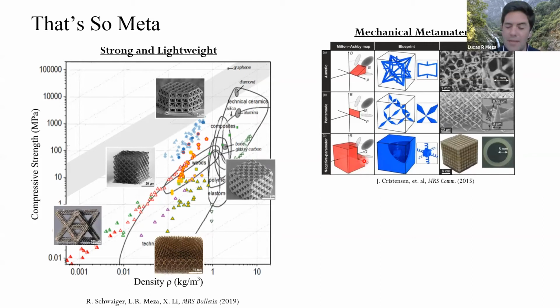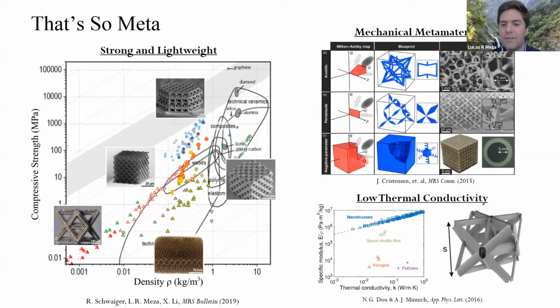There's other non-mechanical properties as well. So this is some work out of Caltech that we had collaborated with Austin Minnich on over there. He's a professor at Caltech on ultra low thermal conductivity materials. So it turns out when you start to make these ultra lightweight materials, you get ultra low thermal conductivity because there's nothing there to conduct the heat.